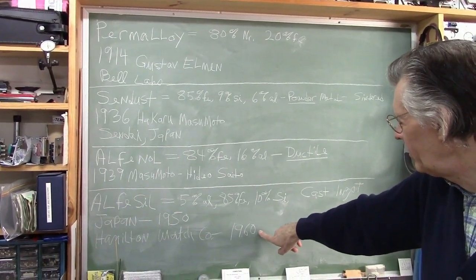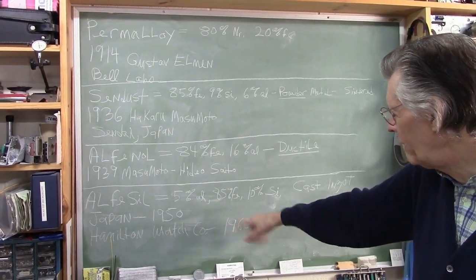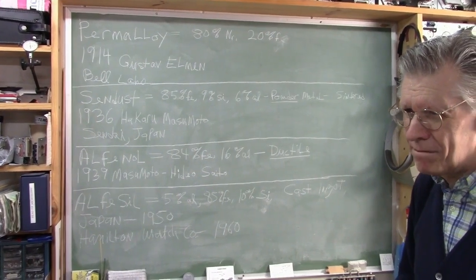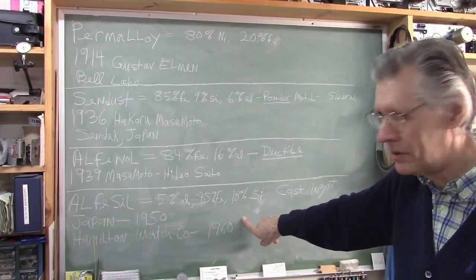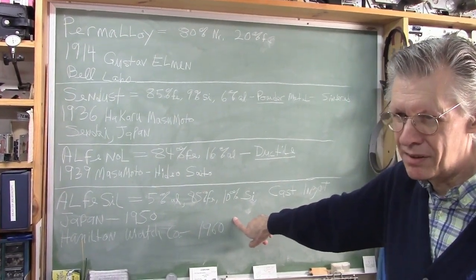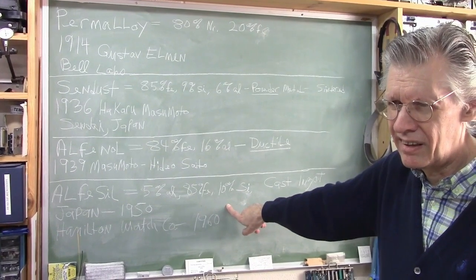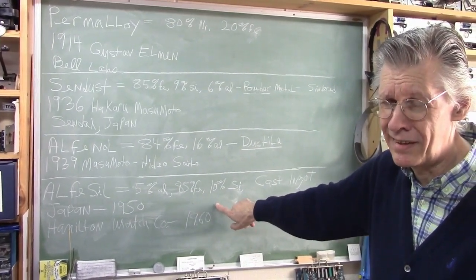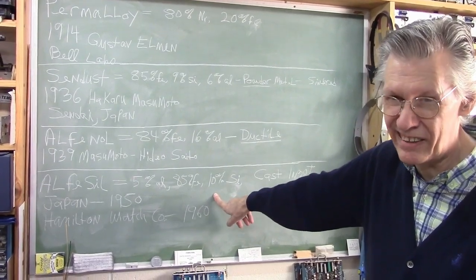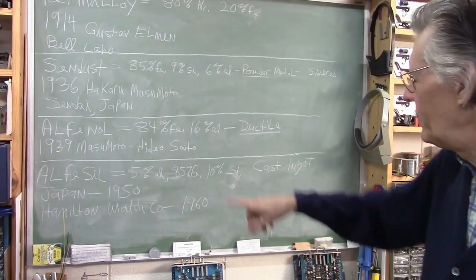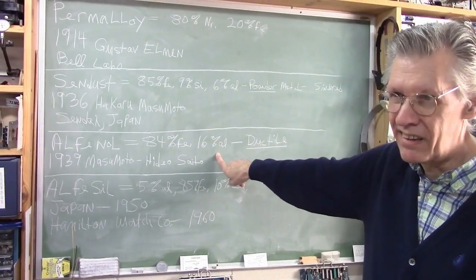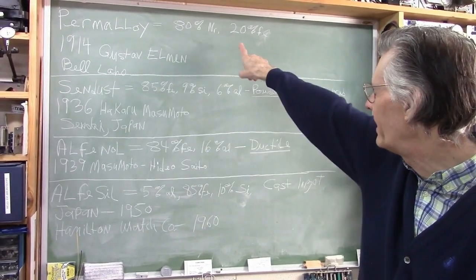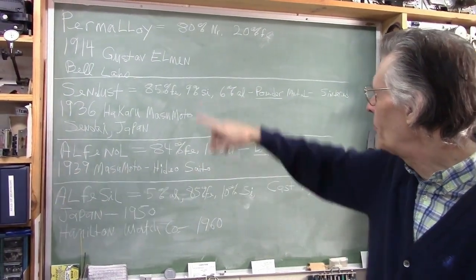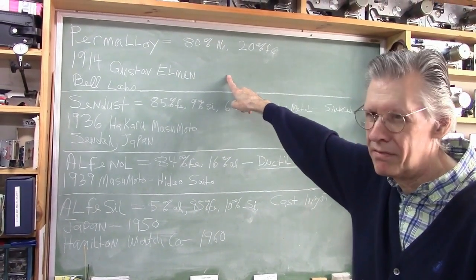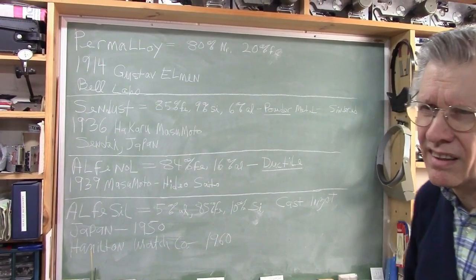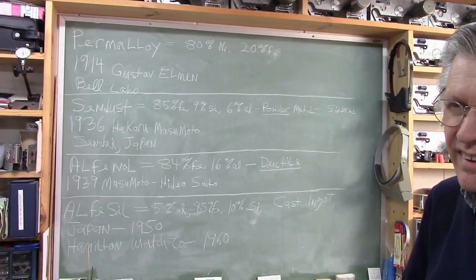And then of course after the Alfesil became available in the 60s, Alfesil from then on became the predominant material of choice because it has a very low wear rate. You get a lot of hours, 300-400 hours on an Alfesil head, whereas you could only get maybe 100 on alphenol, and then even less on permalloy. Permalloy has found its use mainly in longitudinal heads, such as audio heads.